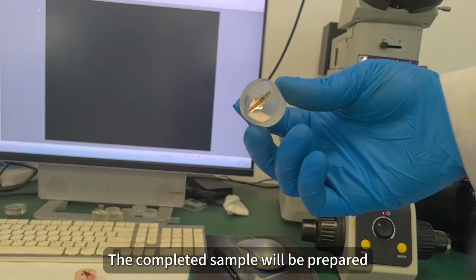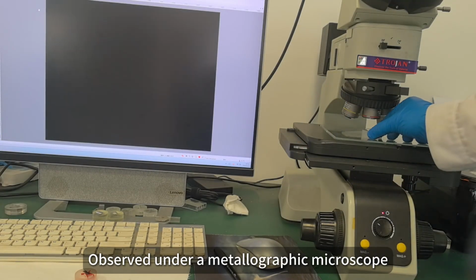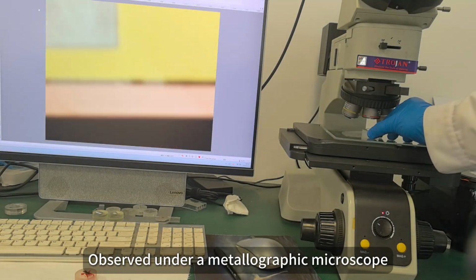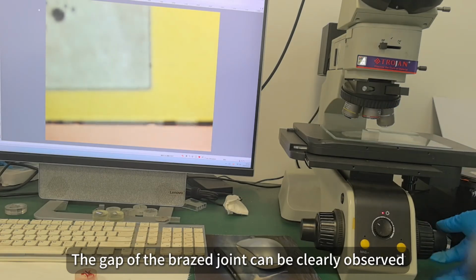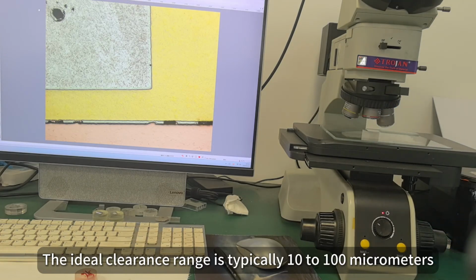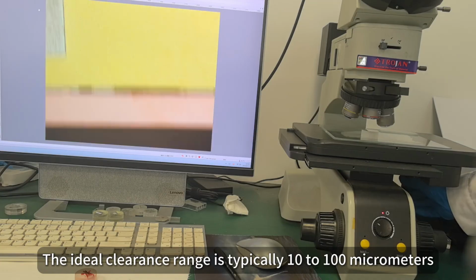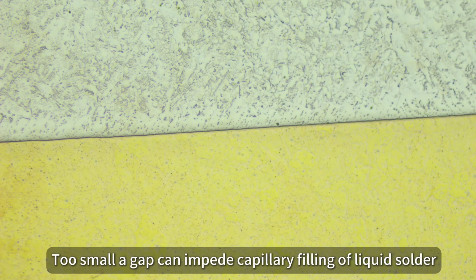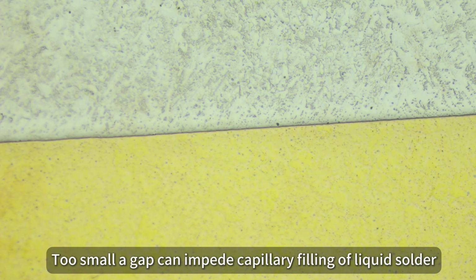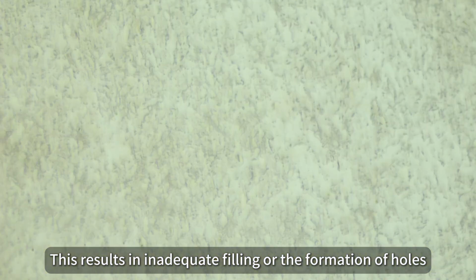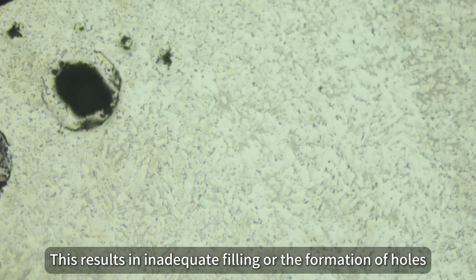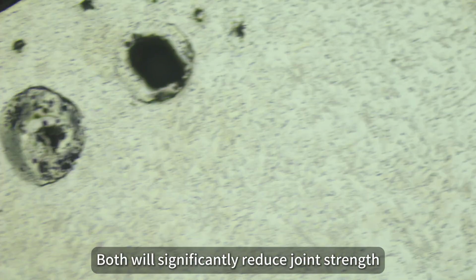Observation. The completed sample is observed under a metallographic microscope. The gap of the brazed joint can be clearly observed. The ideal clearance range is typically 10 to 100 micrometers. Too small a gap can impede capillary filling of liquid solder. If the gap is too large, this results in inadequate filling or the formation of holes. Both will significantly reduce joint strength.